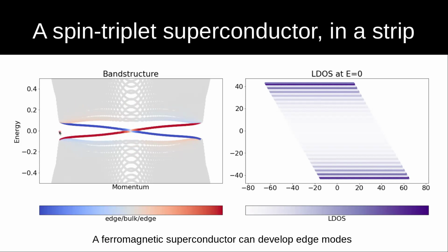And let me emphasize again that this is a superconducting state, and that when you measure it in the bulk, you see a gap. When you measure it at the edge, you see gapless excitations. Of course, the nature of these gapless excitations is essentially topology. So these unconventional superconductors effectively have topological states, and these topological states are associated with a finite Chern number.